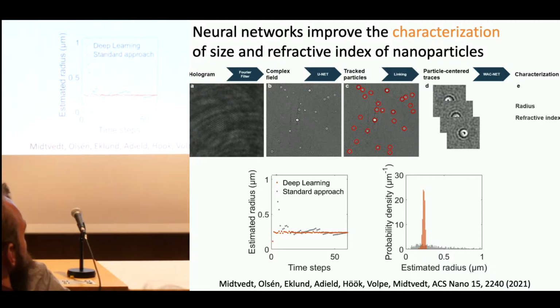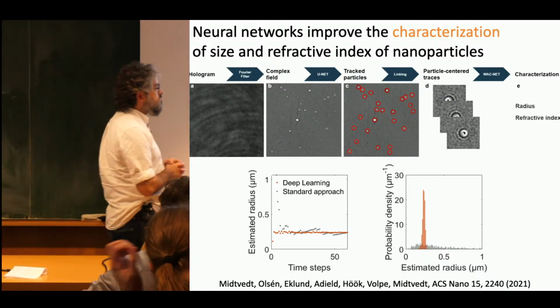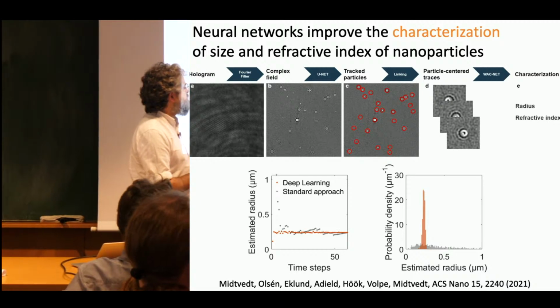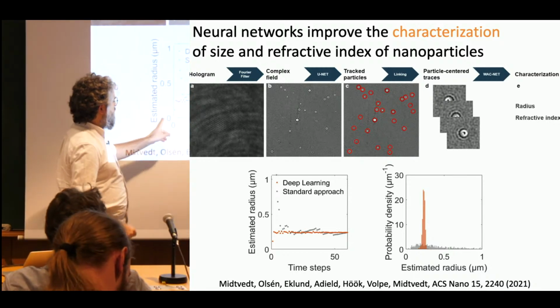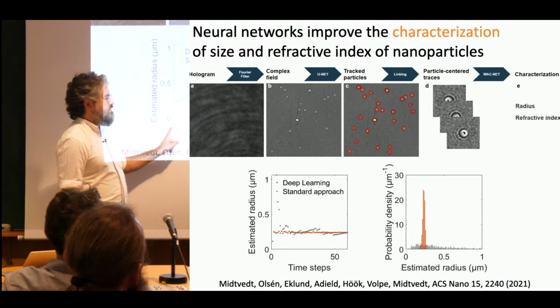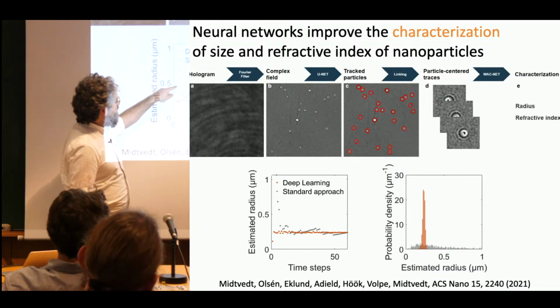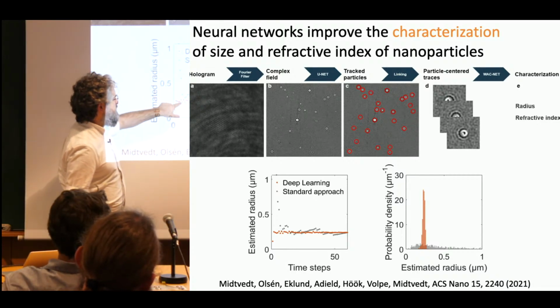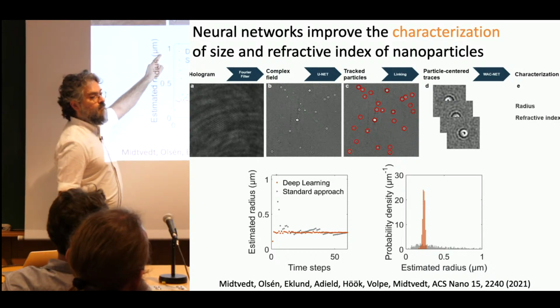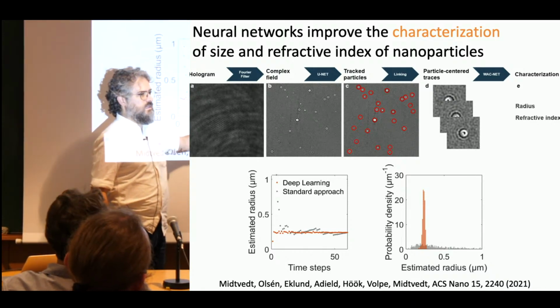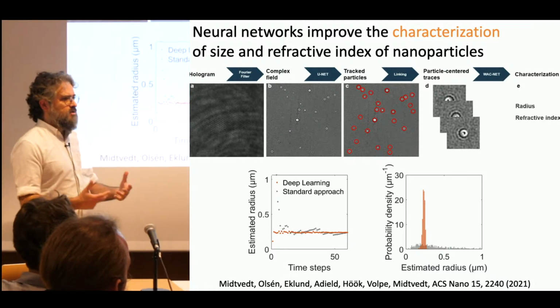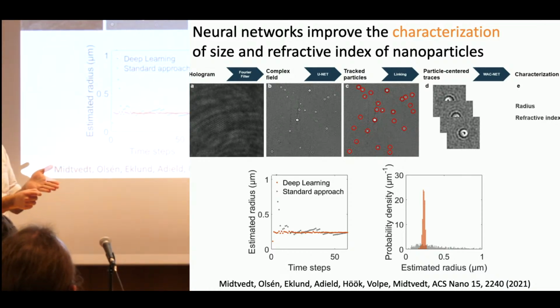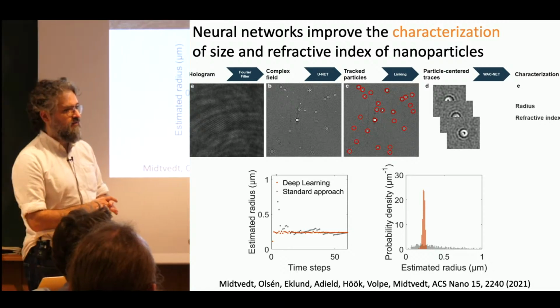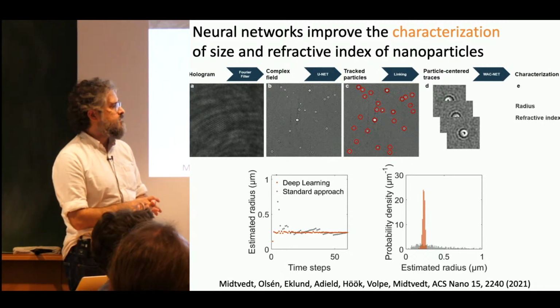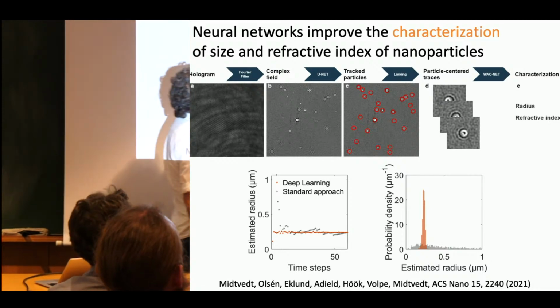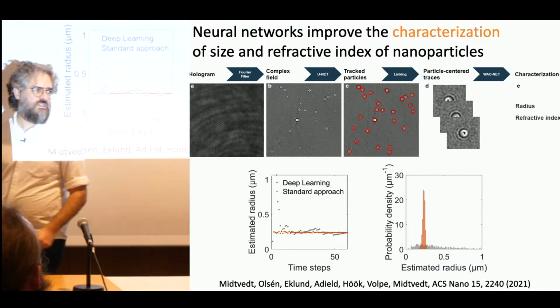Okay, so we can even, yes? Just one question. On the left, it seems that the standard method is estimating the radius. Here is the number of time steps that we use for the estimation. And you see that the standard method, which is the gray one, gets it very wrong. This is the actual value. It's not 1. But it approaches that value, of course, if you have enough time steps, yes. Because the standard method essentially takes a trace of the particle, calculates the mean-square displacement and derives the radius from the diffusion constant. So on the right, we are seeing like the first. Yes. This is done for the case, I think, if I remember correctly, for 5 time steps.